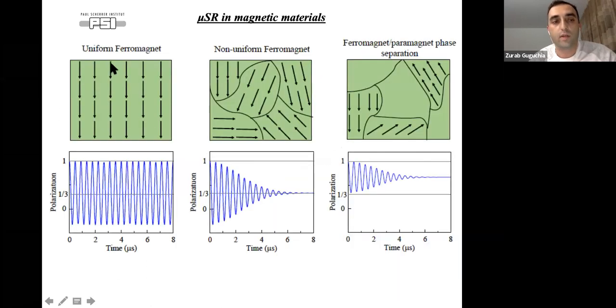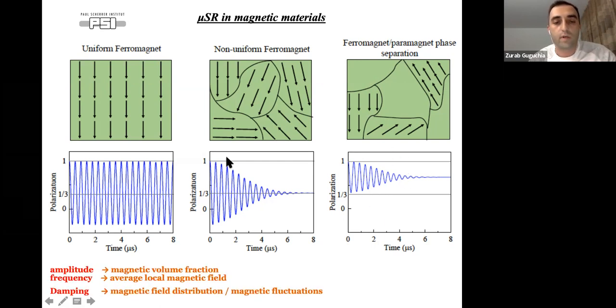Now, if you have a magnetic material, depending on whether we have a uniform ferromagnet, a non-uniform ferromagnet, or phase separation, we expect different time spectra. If you have a uniform magnet, then you have no damping at all, and the frequency is proportional to the moment size. If you have a non-uniform domain distribution, this causes the damping of the spin polarization, which is proportional to inhomogeneity. And if you have phase separation, then the amplitude of the signal is reduced, and you see it directly on the spectra. So by carefully measuring the muSR spectra at different temperatures or pressure and so on, we can extract separately the information on the magnetically ordered volume fraction and the ordered moment size, which is an advantage compared to neutron diffraction. And we can also learn about magnetic field distribution or magnetic fluctuations inside the magnetic material.